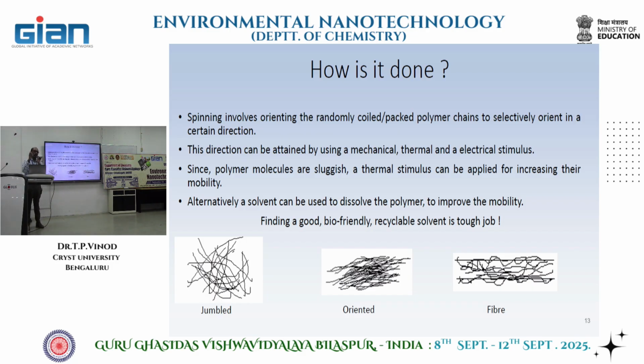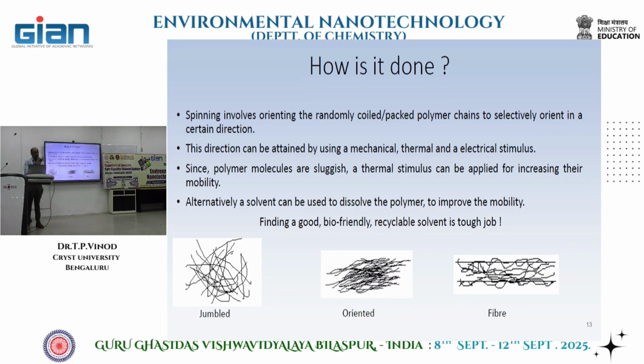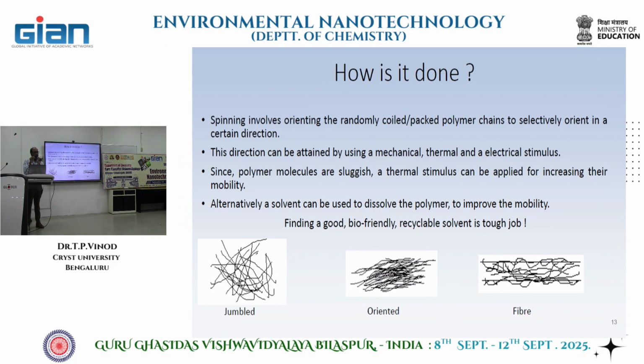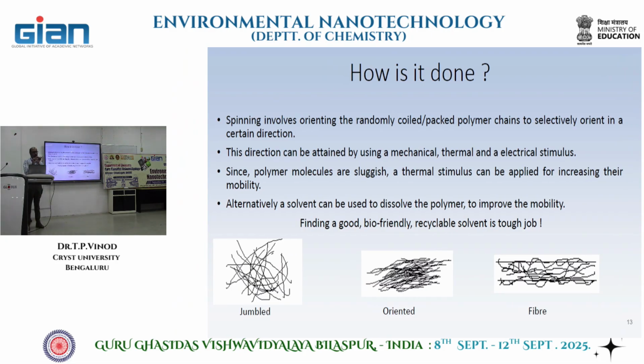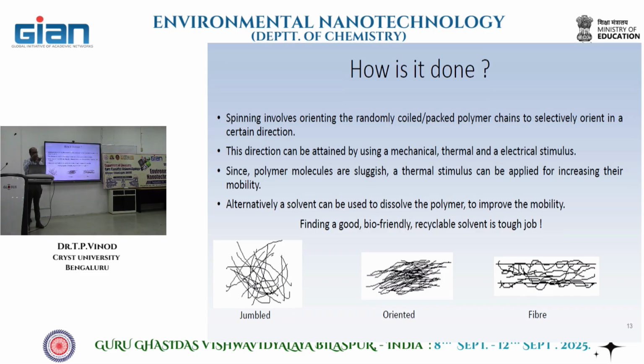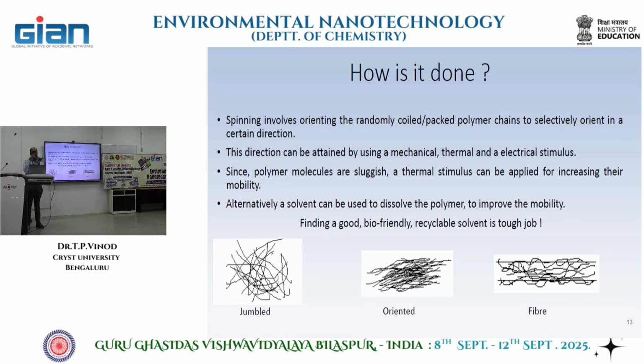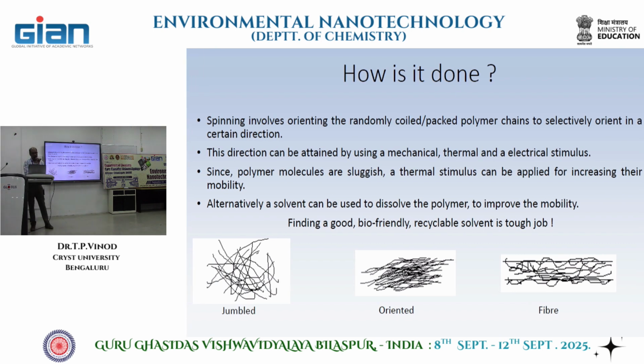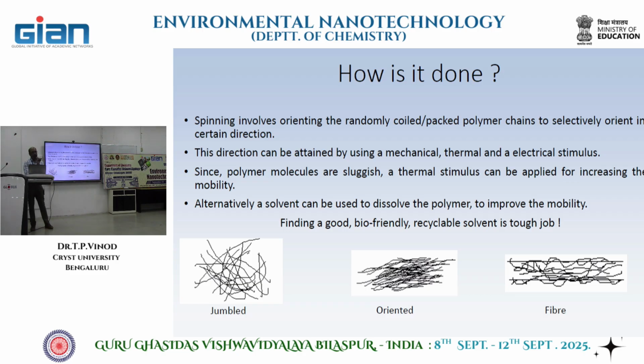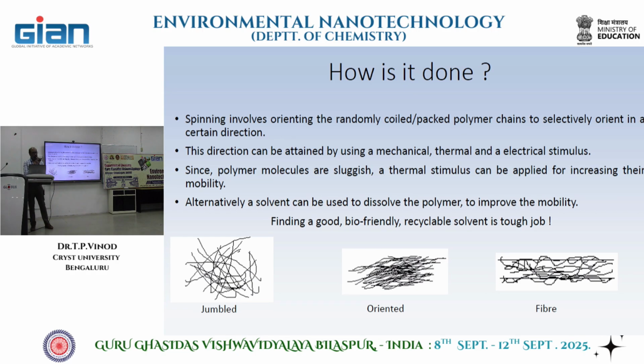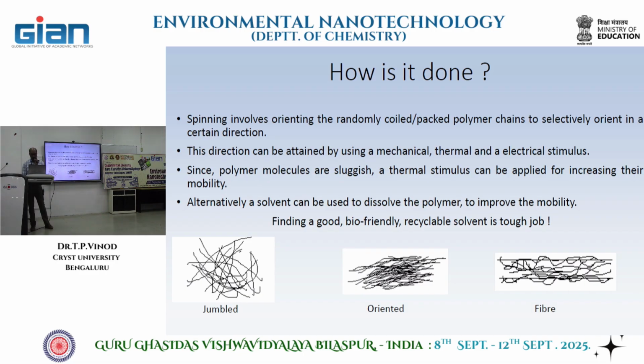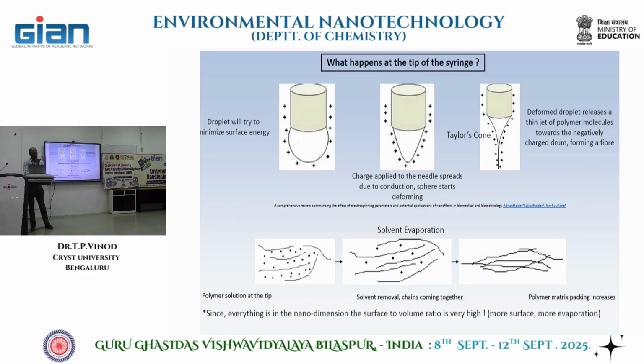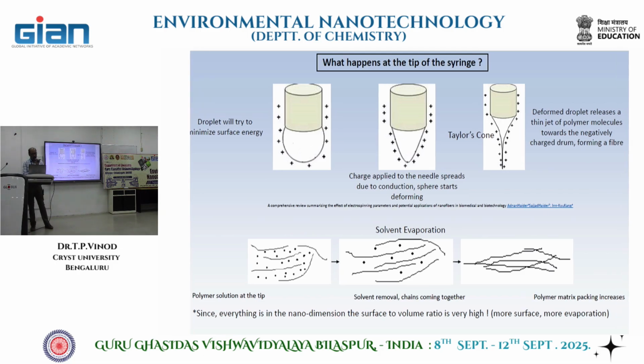Initially, when you are dissolving this polymer in a solvent, it has a very random organization. The polymer strands are jumbled, not organized. But once you apply this voltage, and due to the formation of this Taylor cone and the ejection from the tip, you are achieving orientation of the polymer. So this is a much more organized structure than the normal one. This is something which happens.